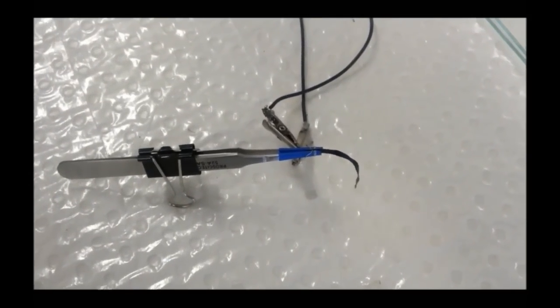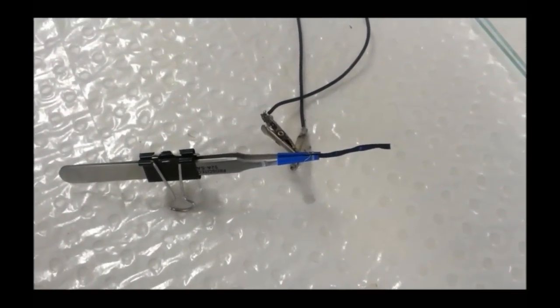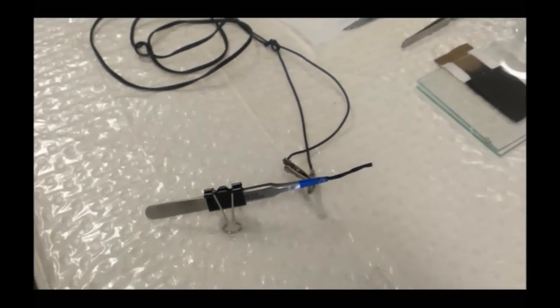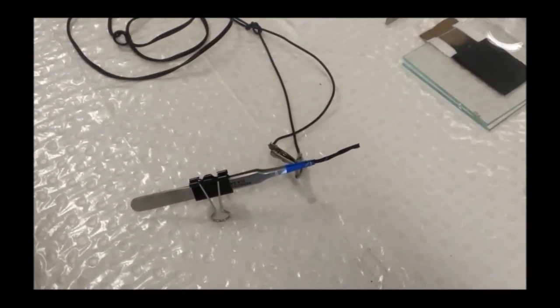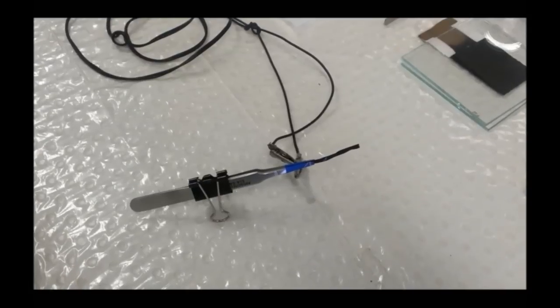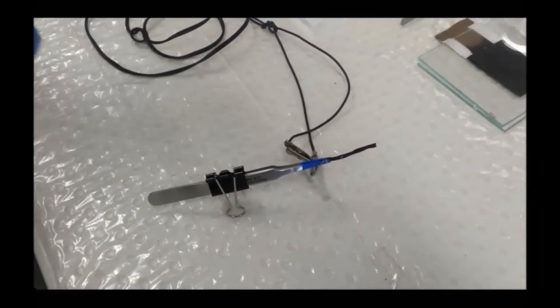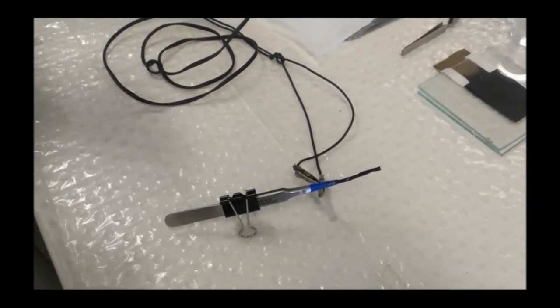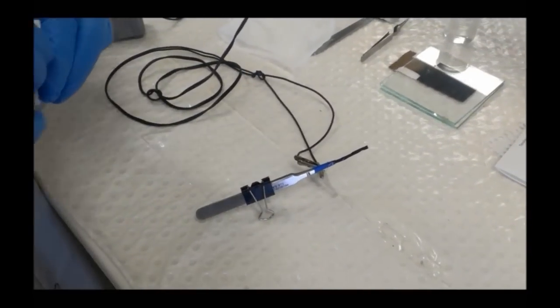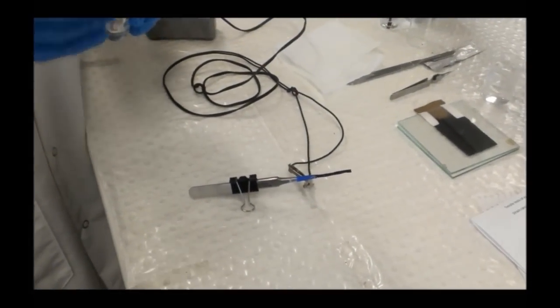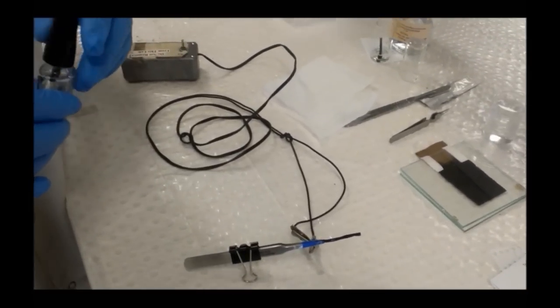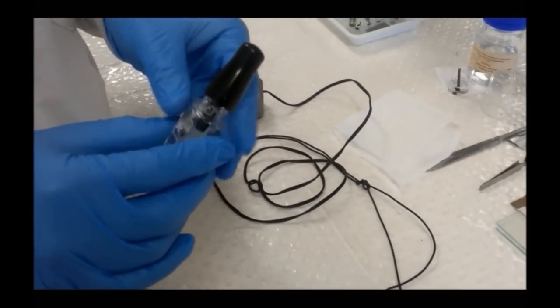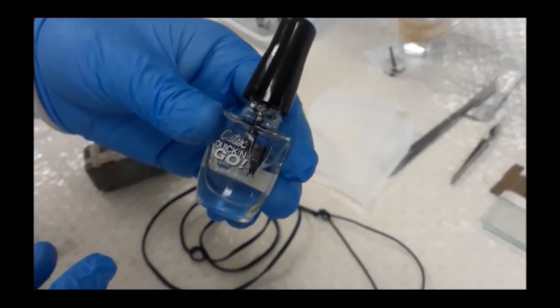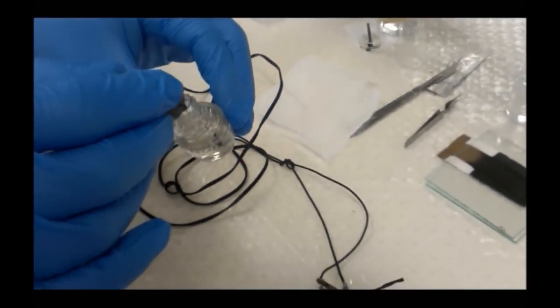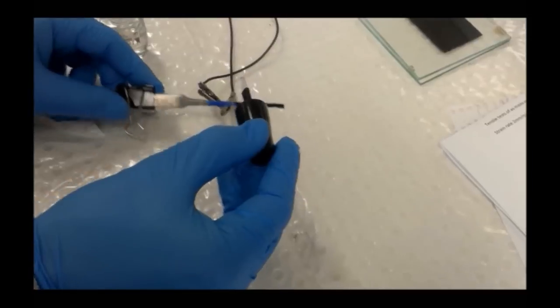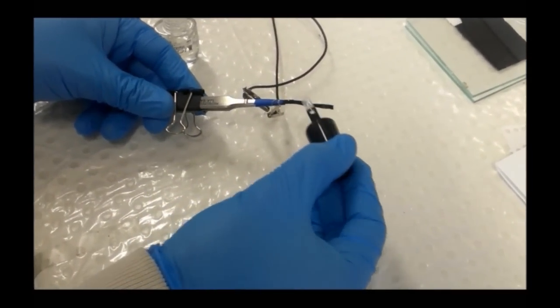Now that will diminish over time as the electrolyte slowly evaporates, and that's one reason why we use propylene carbonate. It's slower to evaporate than water. But if the actuator system was placed into a water bath, then the electrolyte would disappear pretty quickly and we wouldn't see very long response. So we've developed various different encapsulation systems. The easiest, but perhaps not the best performing, is just to use some acrylic nail polish, which we can simply paint onto both surfaces of the actuator,